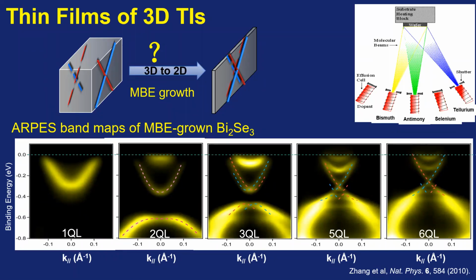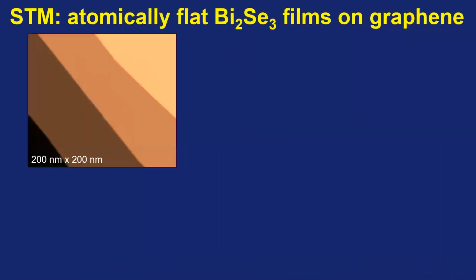When the thickness is below 6 quintuple layer, there is a gap opening, especially between 3 quintuple layer and 5 quintuple layer. We can see the Rashba splitting. This Rashba splitting is just induced by the top surface state and the bottom surface state hybridization. Besides ARPES, we also use the STM to check the quality of the film. We use STM and ARPES as the group's eyes to characterize the film quality.